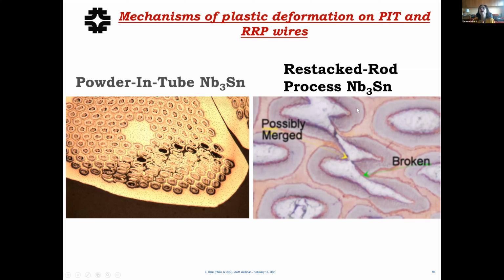So for instance, when we measured the magnetization of this wire, we found magnetization curves with an amplitude that was much larger than in the round wire, because the magnitude of the magnetization behavior in these materials depends on the size of this filament. So once they start merging together, you produce a much larger magnetization. And this is why our magnets didn't work, because the magnetization was way beyond the value that would make them work at the low field. It's called low field magnetic instabilities. When you have your superconducting filaments that are too large, your magnets are magnetically unstable.